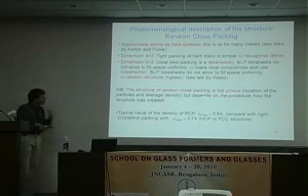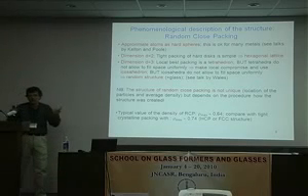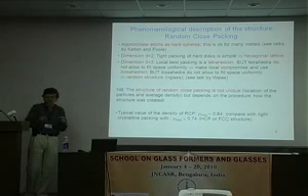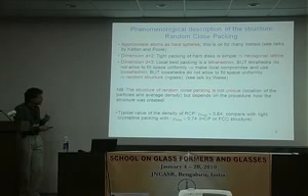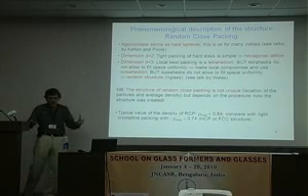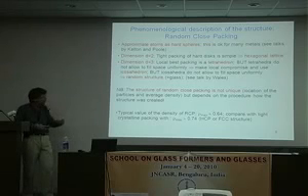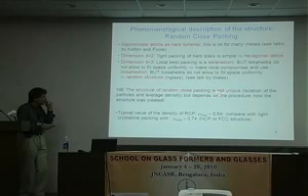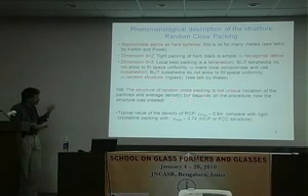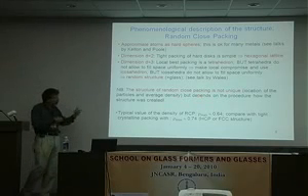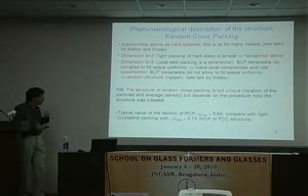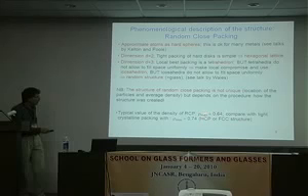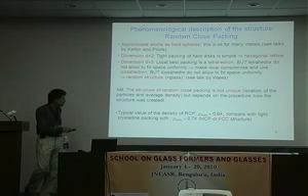makes that the final structure from a microscopic point of view is not unique, that is, the location of the particles is not unique. But, and this is not surprising, what is more surprising is that even the average density of the structure that you get depends on the algorithm that you're using. It changes by a few percent, okay? And so there are people still working hard these days in order to understand what is really going on. In order to give you an idea, for random close packing of hard spheres, you get a packing fraction or density of particles which is around 0.64.